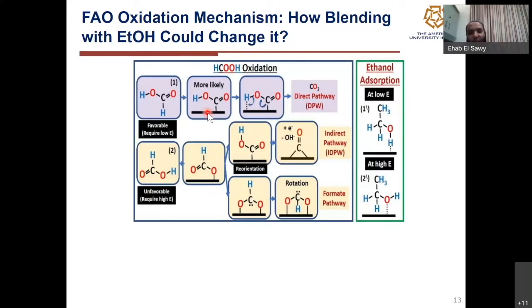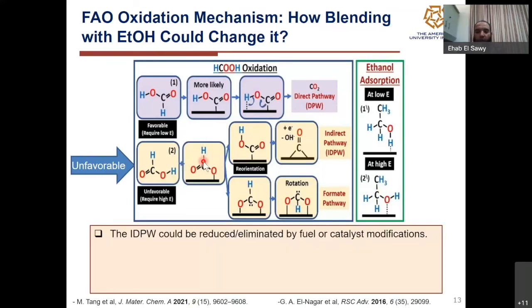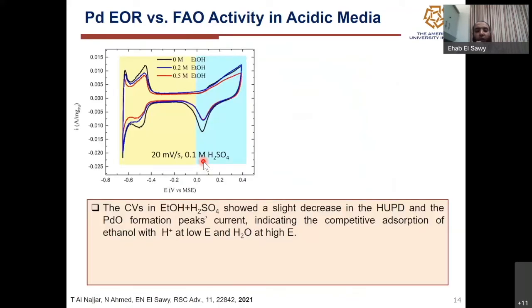Sure, thank you. Palladium is considered the most active catalyst toward formic acid oxidation. So we wanted to see how ethanol may enhance or interrupt formic acid oxidation on palladium, and how it may hinder the indirect pathway for formic acid oxidation, through competing in the adsorption. The ethanol oxidation on palladium is inactive, which means no current will come from ethanol oxidation. So all that can happen is an enhancement effect or maybe an inhibition effect.